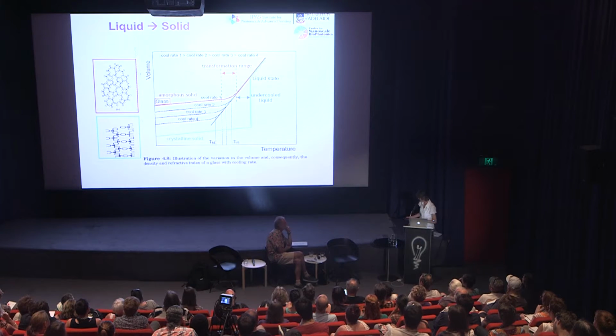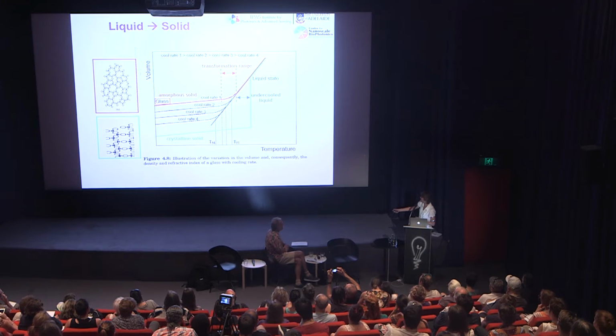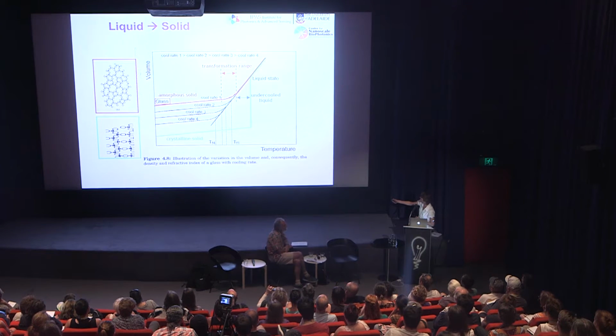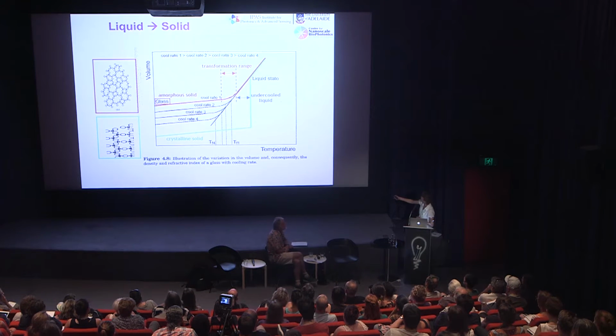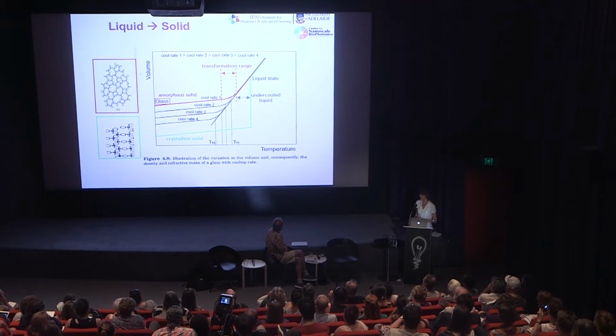This is shown here in a scientific way. If you start, here's a property, it doesn't really matter which one it is, and here's the temperature. So if you have a melt, what's happening? You cool down the melt. If you have a crystal, at the melting temperature or the crystallization temperature, you have a sudden change in the property, and then again a gradual change. This is not happening with a glass melt. What's happening there? It continues the gradual change, goes then through the glass transformation region, which you already heard about today, and then it cools down further.